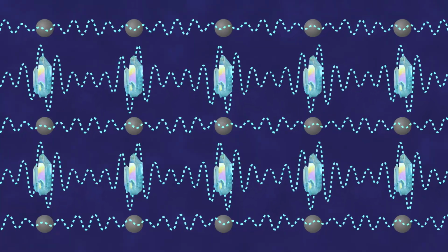Such an upconversion material, made up of two types of nanoparticles, metallic spheres to concentrate the field, and crystals containing ytterbium and erbium atoms to perform the actual upconversion, can achieve a conversion efficiency of infrared radiation into visible light of up to 10%.